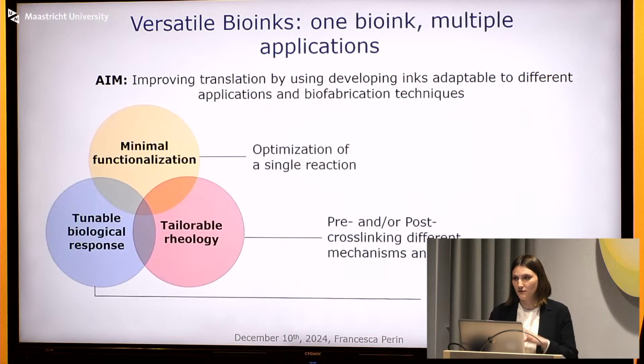We identified 3 pillars of what we wanted for our versatile bioinks. So one was minimal functionalization, and this was to make testing faster. And of course, for it to be versatile, we really needed the rheology to be tunable, both before and after deposition, so that we could adapt it to different techniques, but also we could adapt the viscoelastic properties to different tissues after cross-linking. And of course, we would need to tune the biological response of the gel.